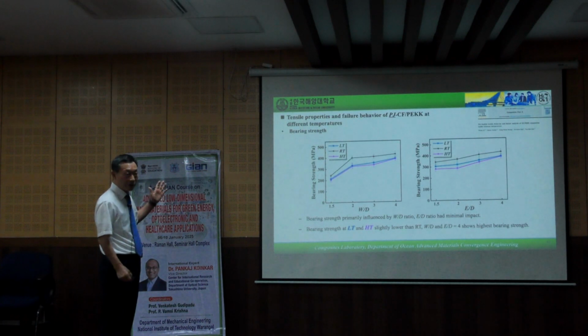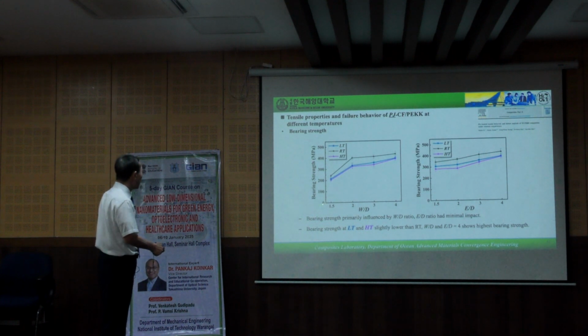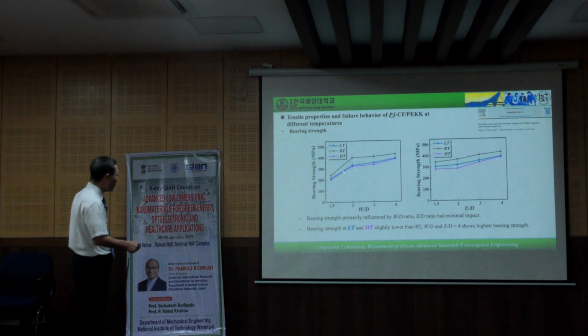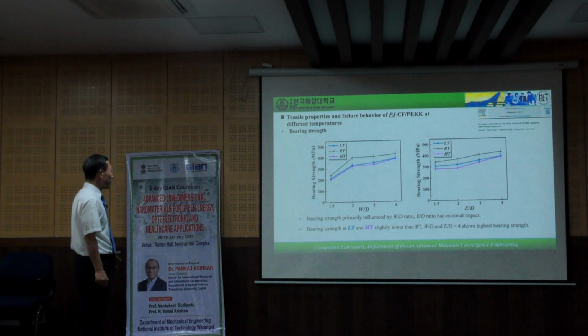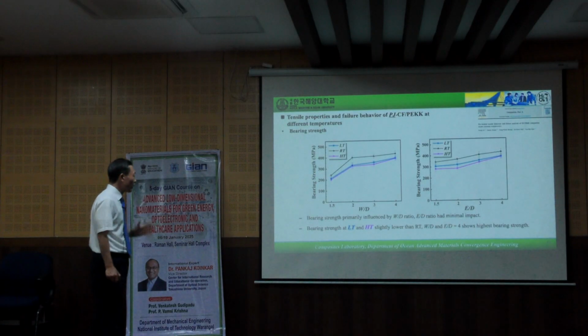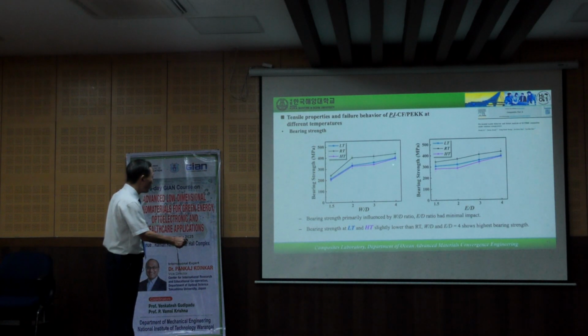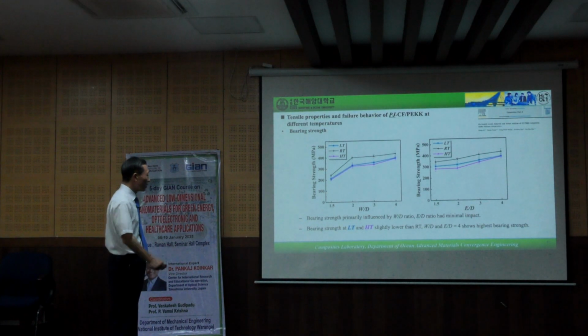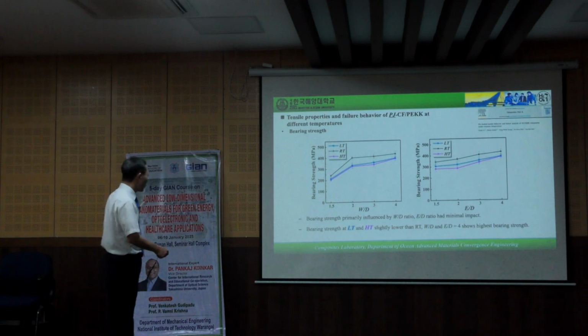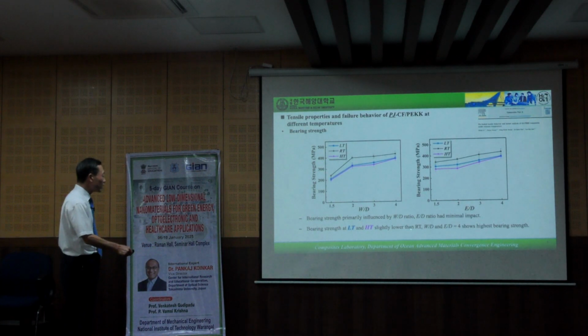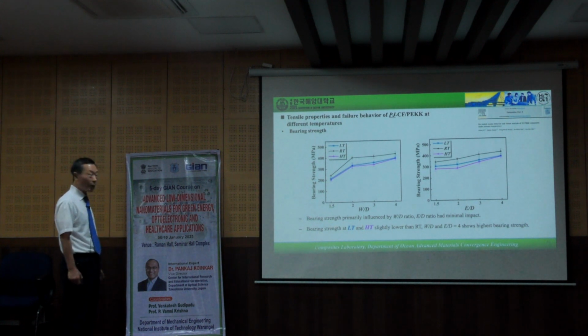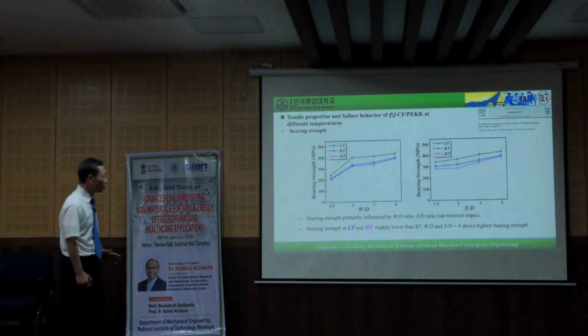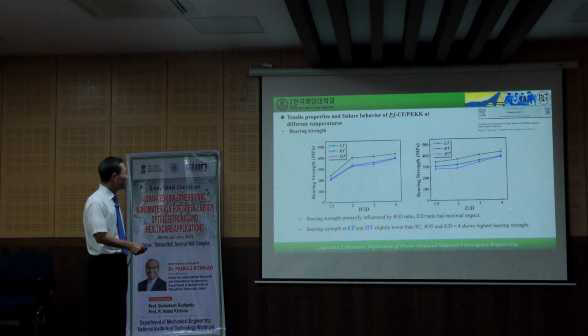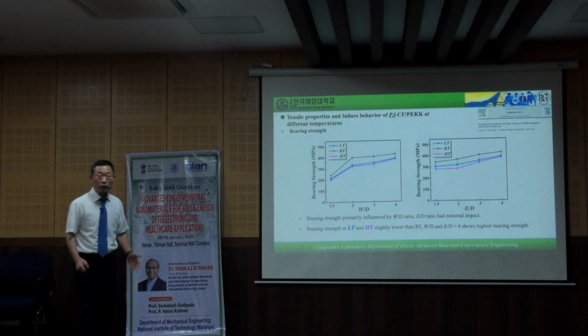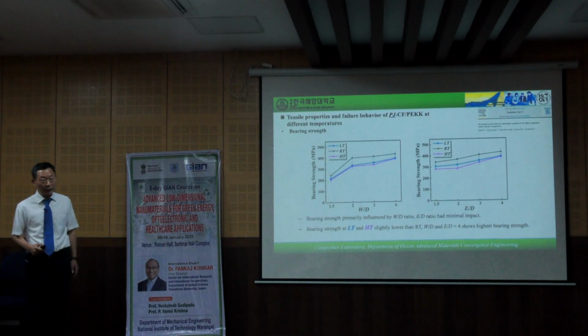Just we'd like to compare the bearing strength. Between bearing strength and the W/D ratio shows right there. Bearing strength primarily influenced by W/D ratio, right? And E/D ratio had minimal impact. Also, bearing strength at the low temperature and the high temperature slightly lower than room temperature. W/D ratio 4 and E/D ratio equal to 4 shows the highest bearing strength. This is also a very important result as a bearing strength.